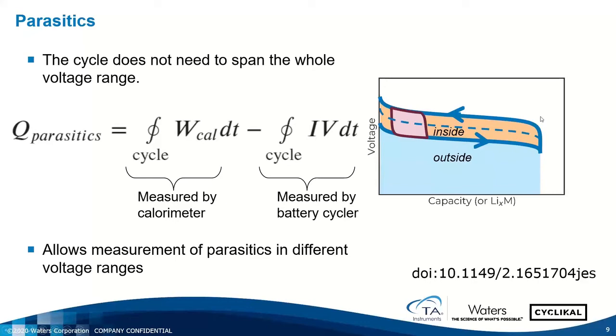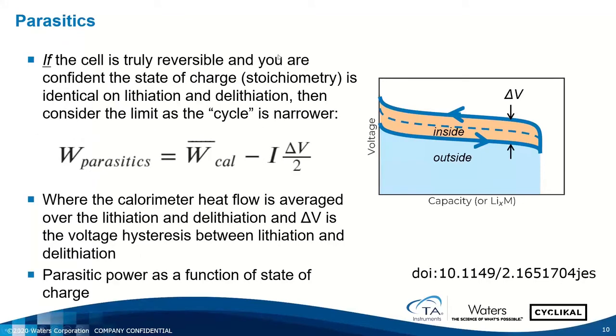So I can do a full cycle, I can do a narrow cycle, but if I know that my cell is truly reversible and I'm confident that the state of charge, the stoichiometry, is identical on lithiation and delithiation, on discharge and charge, then I can consider the limit as the cycle gets narrower and narrower. Let me explain what I mean by that. If I'm charging and discharging, so let's say I'm following this path on discharge and this path on charge, if I'm confident that at this point the X in my material is the same, that I have the same state of charge here as I have here, then I can say that at that exact point my entropy term cancels.